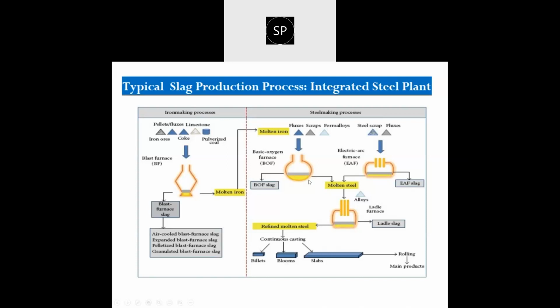During this particular process, the amount of slag which is generated inside the furnace is around 150 to 200 kg per ton of steel production. So around 15 to 20% slag generation is there in case 1 ton of steel is required to be produced inside the furnace. So this type of slag is huge in volume and poses significant disposal issues to the different steel industries, and therefore we developed its utilization as a road construction aggregate. And in a subsequent slide I will show you how it can be done.